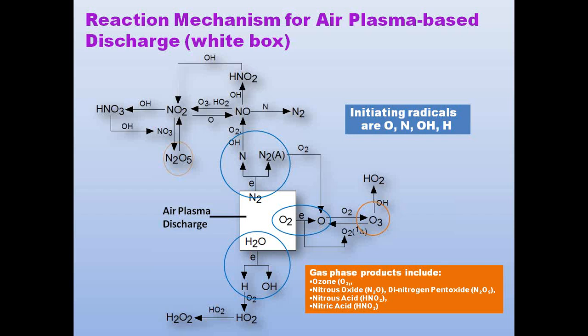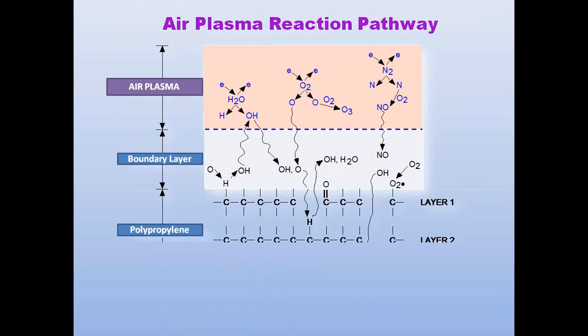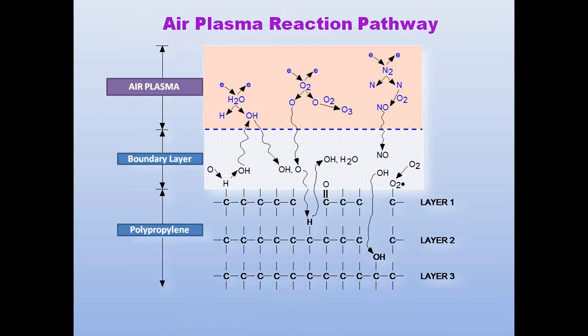If we follow this reaction pathway, again, to the surface of a polypropylene substrate, you can see that these discharges ultimately make their way through a boundary layer, and that boundary layer is typically an atomic surface layer at the material, or into the atomic layers of that material, and you see different types of functionalizing effects. In this case, we're representing the water vapor, the oxygen and the nitrogen in air, ultimately ionizing into those free radical groups, free radical species, making their way and attaching themselves through that free radical effect and that abstraction effect to the surface of the polypropylene.